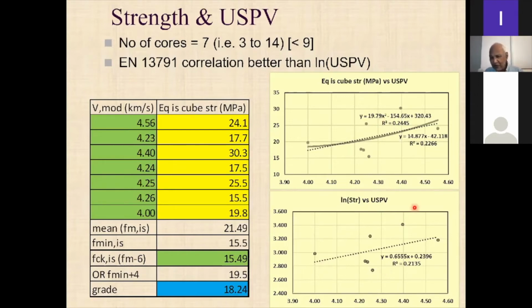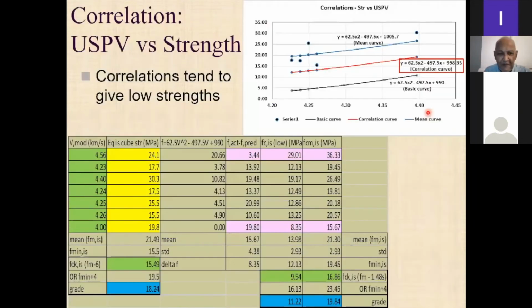It'd be difficult to get good fits; these R-squared values are not very good, but at least you get a slightly better R-squared value for this polynomial compared to this logarithmic one, right? So basically I'm agreeing with the Eurocode, even though this is something that we used earlier, right? Of course, both of these are better than, no, actually this is better. This is a simple linear regression, right? But anyway, let's stick with this polynomial. Okay. So now this is the equation given in the Eurocode, right?